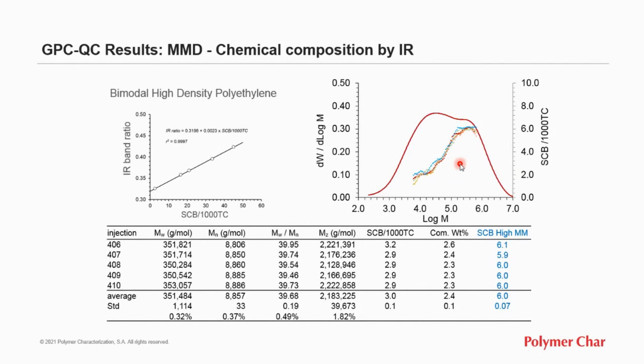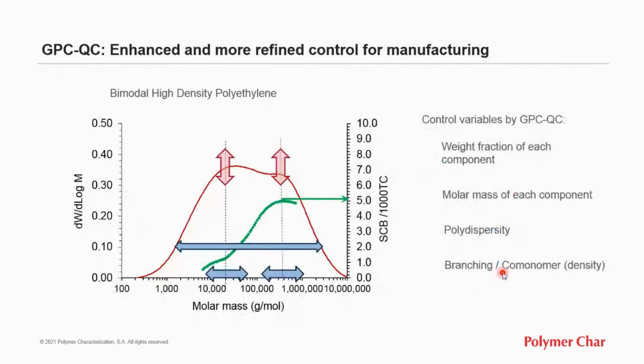polymers which is produced in each of the reactors, but also the level of comonomer and how it is incorporated along the molar mass distribution. In this case, the short chain branching at the high molar mass fraction was quantified.